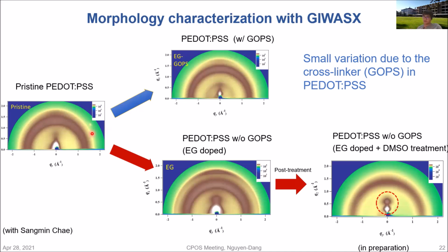However, Sangmin also showed a very interesting result that without the GOPS, if we doped it with ethylene glycol, we have a higher conductivity compared with the pristine PEDOT:PSS. So that is a well-known fact. But now, if we dope it with ethylene glycol and we treat it with DMSO, we see different features. So basically, we may see a highly enhanced conductivity. So one of the experiments I will do next is actually using the PEDOT:PSS without GOPS in order to see that my fabrication techniques, when applied with these materials, may result in a wider range of figure of merit, say conductivity or volumetric capacitance.